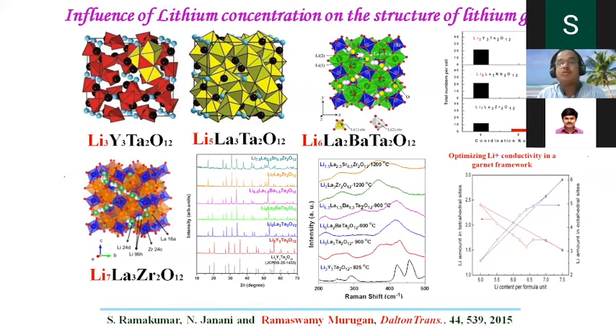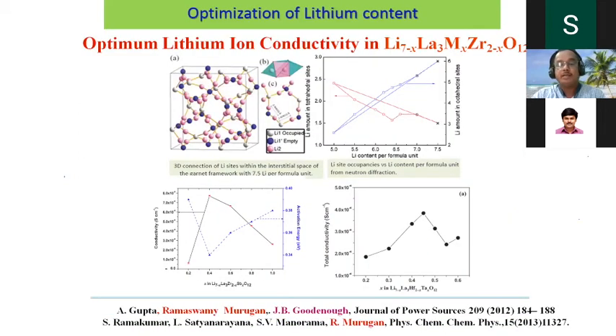Slowly it opens up what we call octahedral coordinations. When the octahedral coordination opens up, some of the lithium jumps from the completely filled tetrahedral sites to the octahedral, and I'm creating partial vacancies in the octahedral and tetrahedral coordinations. When I improve it, it's a perfect ideal condition. I could bring down these bonds. So what will happen? It becomes very easy for jumping, and the activation energy comes down. And this is how I was able to improve the conductivity, moving from Li3 to Li7 in lithium garnets.